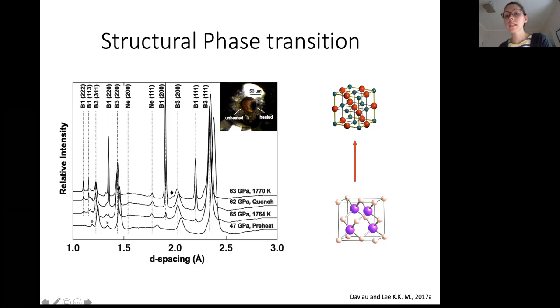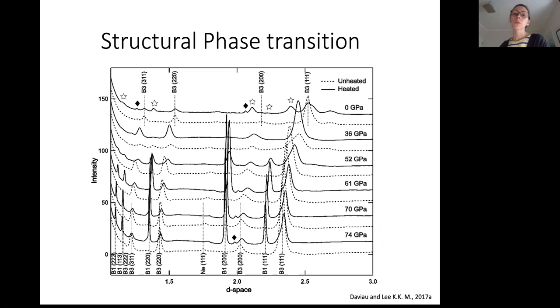So what we're seeing is illustrated in these molecular cubes over here, going from a more open zinc blende structure to a more closed rock salt structure at high pressure. And so once we form this structure, we decompress the sample, and we see that it sticks around until about 52 to 36 GPa. So down here, I have the different phases labeled. If you pick one of these B1 peaks, maybe one that's around, again, a little below 2 angstroms, then if you follow it down, it disappears by the time you get to 36 GPa. So we see some hysteresis in this transition, right? We formed it at 60, but at room temperature, when we decompress it, it sticks around until about 40.